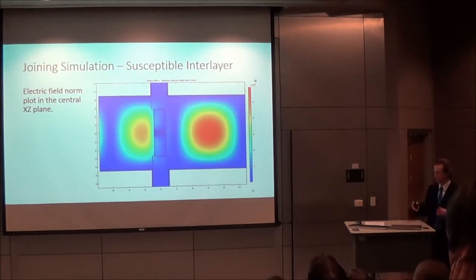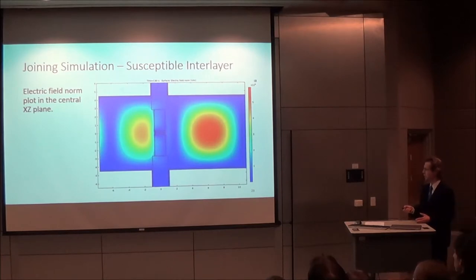The joining chamber and the simulation of the ceramic metal joint is shown here with the electric field plot and the XZ slice of the waveguide. And here you have the ceramic and metal base materials and the interlayer. This dark blue represents a very low intensity of the electric field. And so what you can see here is that where there was a very regular periodic hot spot pattern within the waveguide, that has been distorted by the presence of not only the joint itself, but also the pressure applicator.